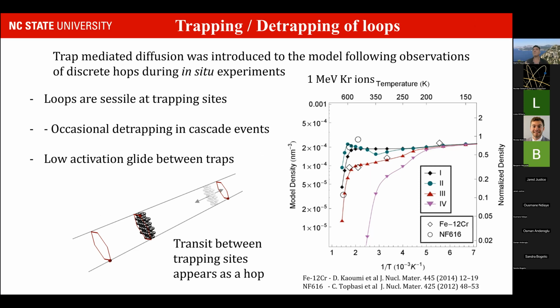And for quite some time, we had a mismatch. The trend of the model was matching the trend of the kinetics of the growth and formation of the defects, but we were off by an order of magnitude or more. For quite some time, we didn't really understand why until we looked again at all the videos and we realized that basically the model was considering a diffusion approach that was not appropriate. And because of the way that I showed earlier in the video, the jerky motion, the hopping of the defects, the diffusion, the model should take into account that aspect. And that's basically what was done.